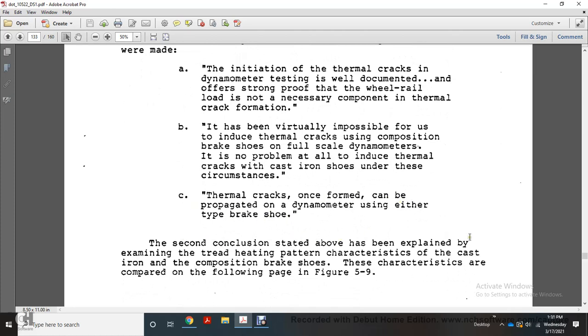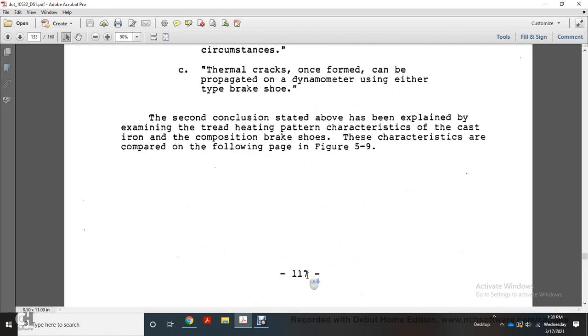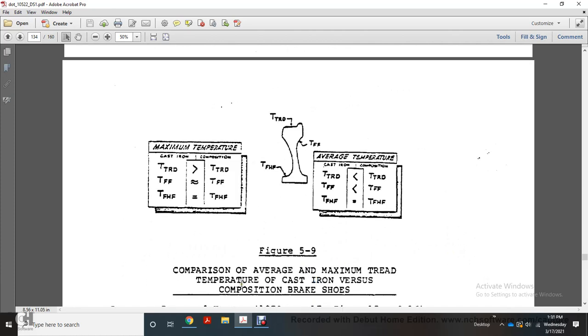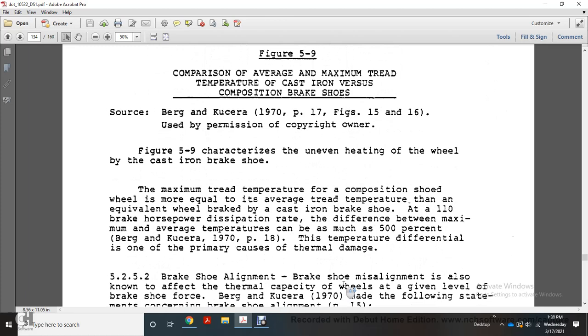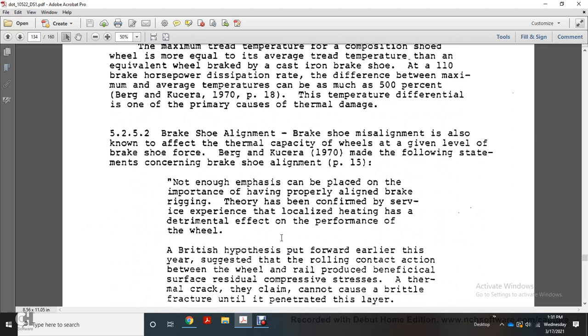The second conclusion stated above can be explained by examining the heating pattern characteristics of cast iron and composition brake shoes. These characteristics are compared on the following page in Figure 5.9. Figure 5.9 shows the comparison of average maximum tread temperature, cast iron versus composition brake shoes. The maximum tread temperature for the composition shoe is more equal to the average tread temperature for the equivalent wheel braked by a cast iron brake shoe at 110 brake horsepower dissipation rate. The difference between maximum and average temperature can be up to 500%, and the temperature differential is one of the primary causes of thermal damage.